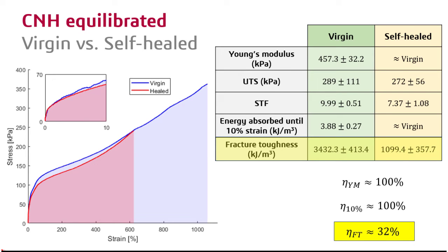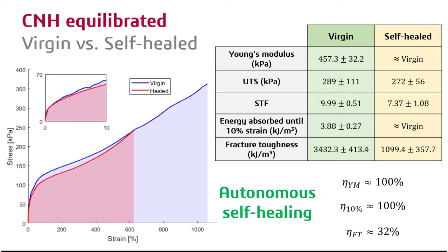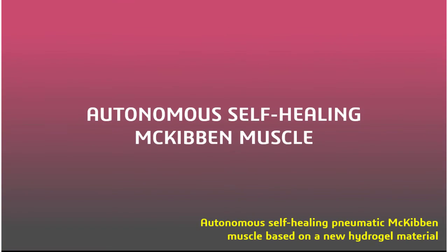This efficiency is obtained dividing the value for self-healed samples by the one for virgin samples. In other words, dividing the red area by the blue area in this case. The conclusion of all these results is that our self-healed hydrogel breaks earlier than a virgin specimen. However, until that point, the performance of our material is really good. And the most important thing, this self-healing doesn't need external stimuli nor agents, which motivates us the use of this material in soft robots. In particular, we developed a hydrogel-based McKibben muscle.